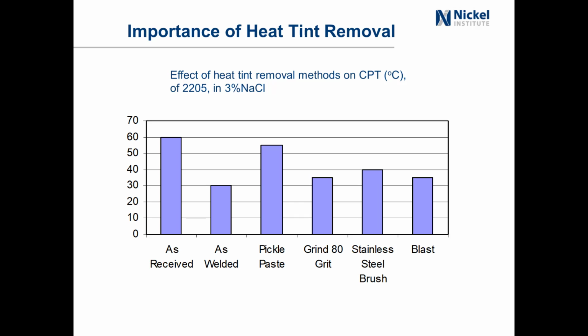And just to show how heat tint and surface finish can have an effect on corrosion resistance, this here is what we call a CPT, which is a critical pitting temperature. In this case, we're testing 2205 in a 3% sodium chloride solution. It's tested in that solution, and the temperature is brought up until the material basically starts to pit. In this solution, 2205, when it comes from the mill, could have a critical pitting temperature of 60. It's not going to pit until it gets to 60 degrees C.